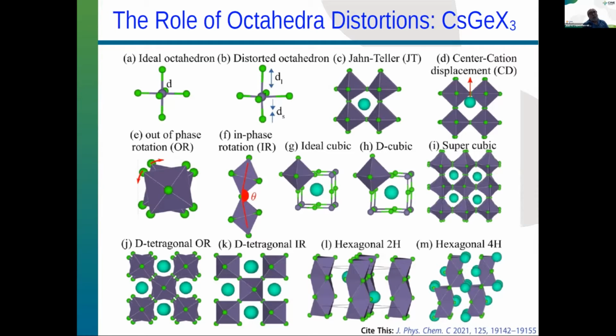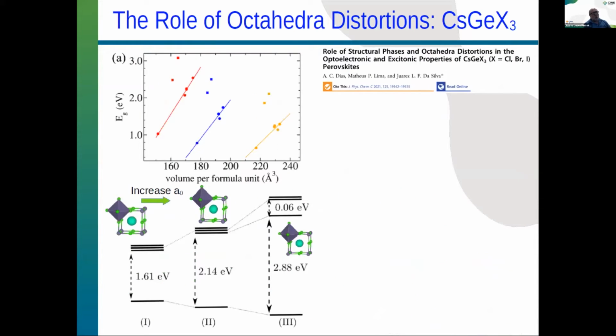And then beyond that, we also can consider different structures, like hexagonal phases 2H and 4H, in which the octahedrons are not fully interconnected in all directions, and it gives something like lower dimensional perovskite structures. By doing those investigations, we considered a large number of structures. In that particular case we considered the prototype cesium germanium X3, changing from chlorine to bromine and iodine. This was very important. And then we picked one of the systems.